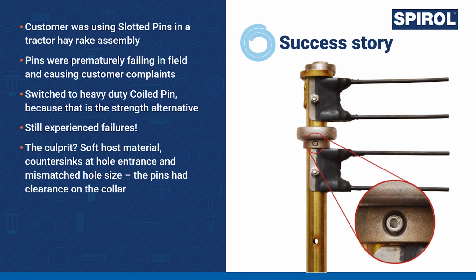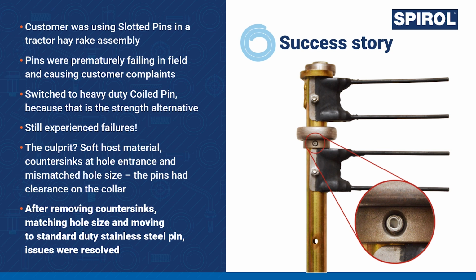It was also discovered that the other spring pins were corroding, even though they were zinc plated. What the hay rake manufacturer didn't realize was that zinc plate is primarily recommended for slotted pins and coil pins only to resist galvanic corrosion where that is of concern, not for atmospheric corrosion protection. This is because for any product that has a hole in it, only the outer diameter and surface gets full coverage of the zinc plate. The inner diameter only gets about one diameter's worth of plating, which is called throw. Because of this, the spring pins were essentially rusting from the inside out.